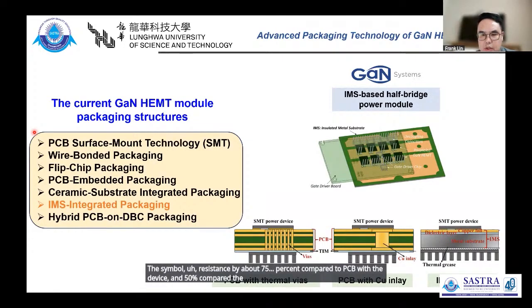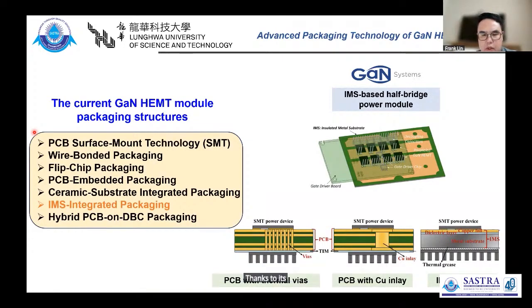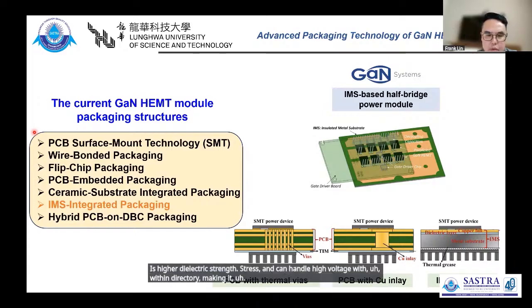In terms of thermal performance, IMS reduces the thermal resistance by about 75% compared to PCB with vias and 50% compared to copper inlay PCB, thanks to its thermal conductivity of 3 to 7 watts per meter-kelvin, much higher than FR4. It also lowers assembly cost by removing the extra heat sink and pads. Although not as thermally conductive as DBC, IMS has higher dielectric strength and can handle high voltage within the dielectric, making it a well-balanced solution for cost, performance, and design flexibility.